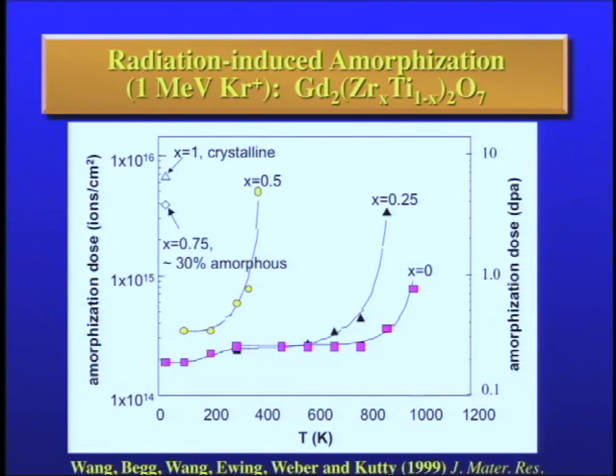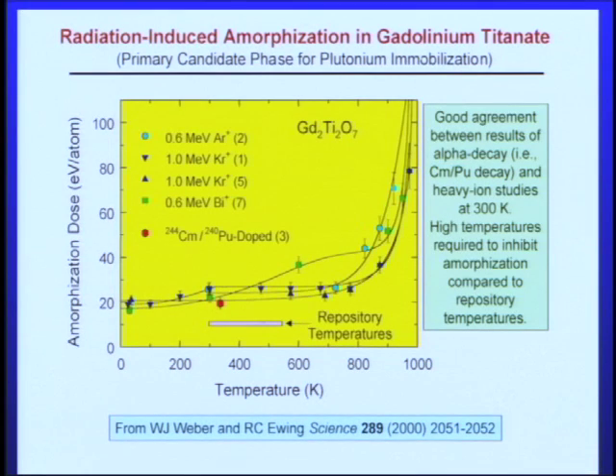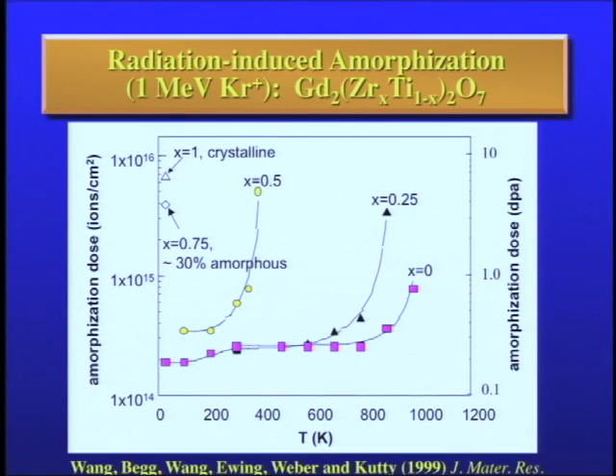Now, the most interesting result is, what if we change the composition? That is, let's substitute zirconium for titanium. This is the gadolinium titanate curve. It corresponds to these curves. And the surprise was that by adding zirconium, the curves move to the left until finally you can no longer amorphize the material. It goes to the disordered defect fluoride structure.